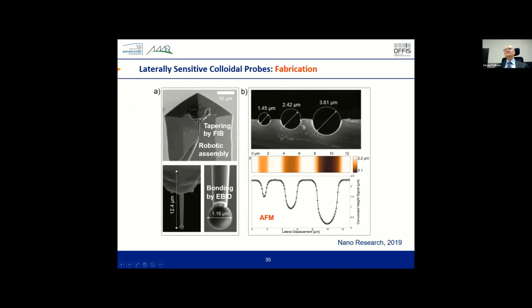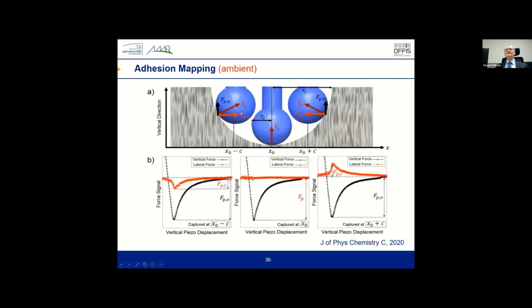So look, this is a real small cavity which you have here, and you have absolutely no problem with your AFM imaging. So your probe works just fine. And this is the implementation of the whole approach for adhesion mapping. So now you can monitor lateral forces as well. This is the red line here, so you can compare. In this case, for example, you don't have lateral influence at the position x0, so you record only your pull-off force, the adhesion force at this point. But as soon as you are on the side wall of the cavity, you can monitor at the same time the lateral force, and you can calculate the real acting force at this point of the texture structure.